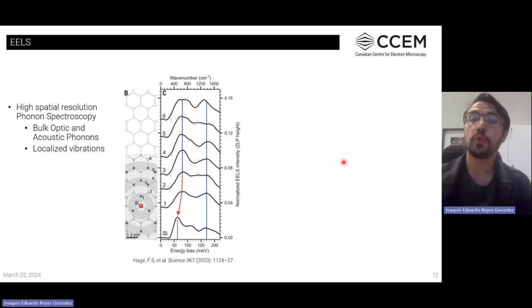Now we can also push the high spatial resolution of the Nion to atomic resolved capability, and explore phonon spectroscopy of bulk systems, so both optic and acoustic phonons, and also localized vibrations associated to impurities or structural features on the system.